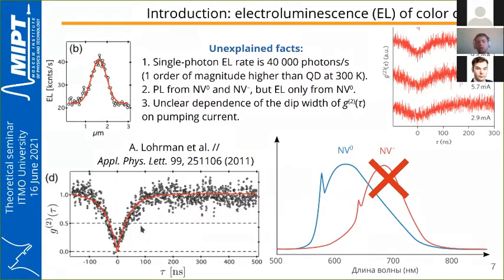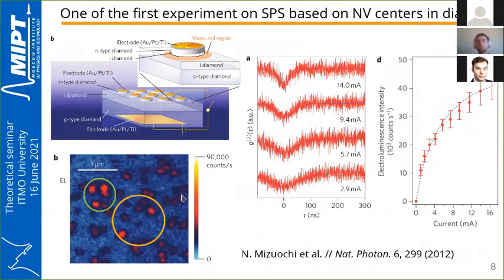However, under optical pumping, it stayed almost constant in the range of 10 nanoseconds, and the nature of this effect was not clear. Here you can see one of the first papers on single-photon electroluminescence from color centers in diamond.